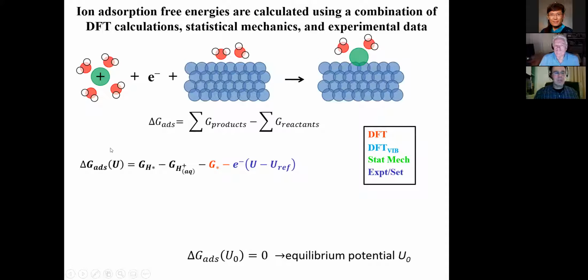So we want to know the delta G of this process: proton in solution, plus electron in our circuit, plus surface that probably had some water on it before we did anything, then puts hydrogen on the surface. Or again, if I'm doing this in reverse, take the hydrogen off by doing the reaction in reverse and create the electron. Delta G is just the free energy of products minus free energy of reactants. And now I have to use DFT or quantum chemistry to do this.